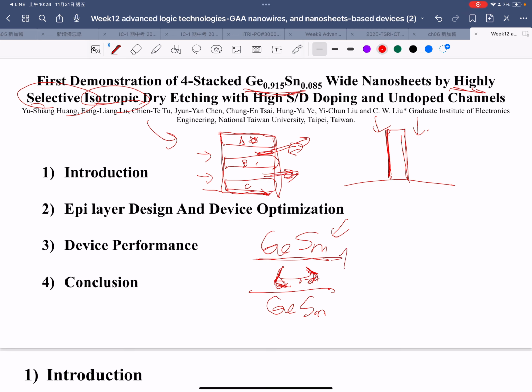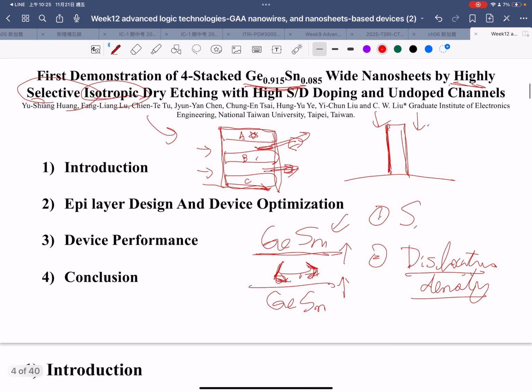But the problem is during the epitaxial growth process, we have to escape dislocation. So two things: S means selectivity. The second one is dislocation density. So epitaxial growth for a superlattice, you have to consider the critical thickness and also the dislocation density caused by the lattice mismatch. So critical thickness is very important.